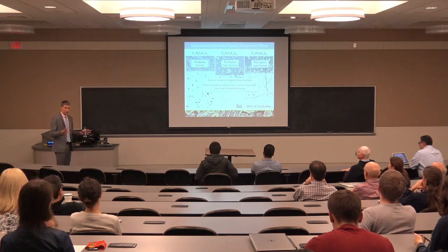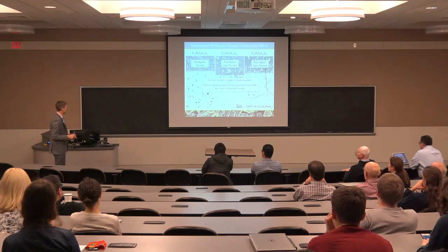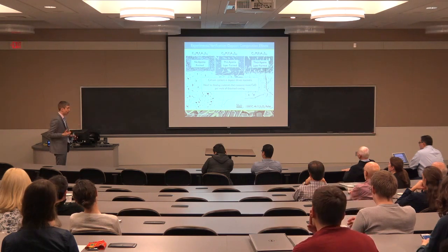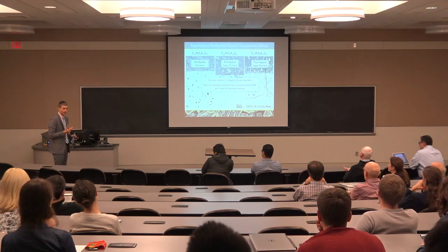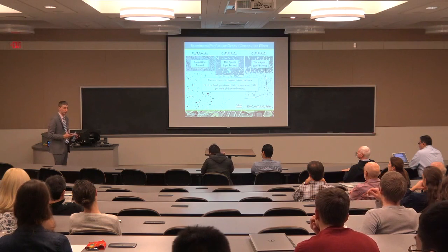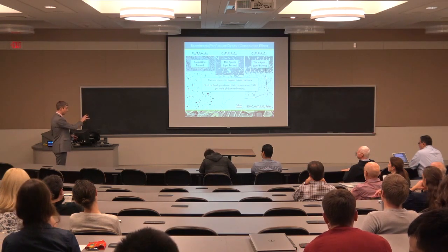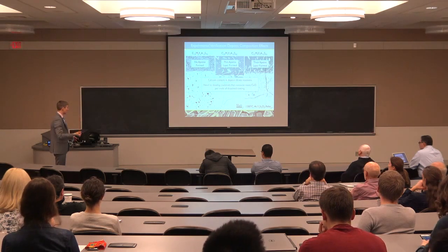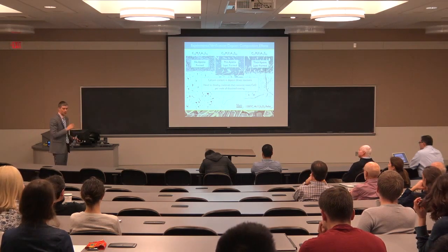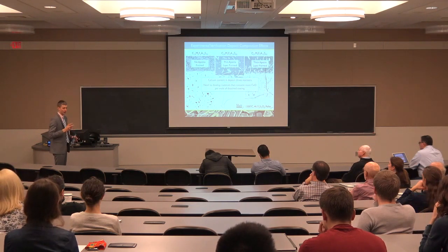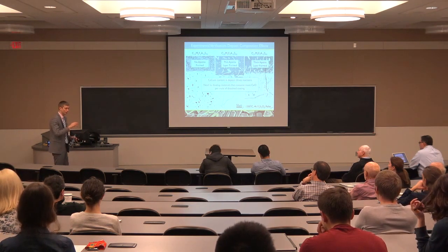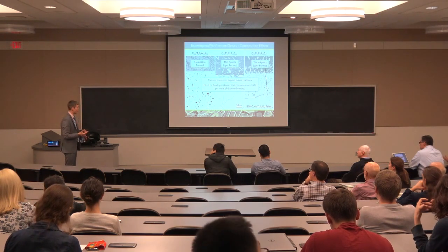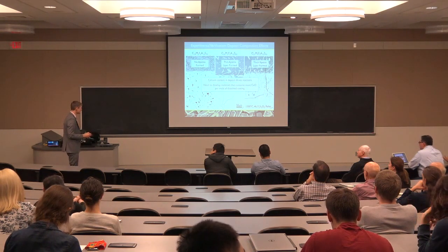And so we have a couple of strategies we can use to potentially design better coatings. One would be to find materials that more actively grab calcium from the melt. The apatite pulls some calcium, but it only has about 12% calcium in it. So if we could find materials to put into the coatings that would go out and grab the calcium more efficiently, that would be a benefit. We already saw from the comparison of the material with and without zirconium that if we put some zirconium in, for instance, we can increase the amount of calcium that goes into the apatite, and that might help us.